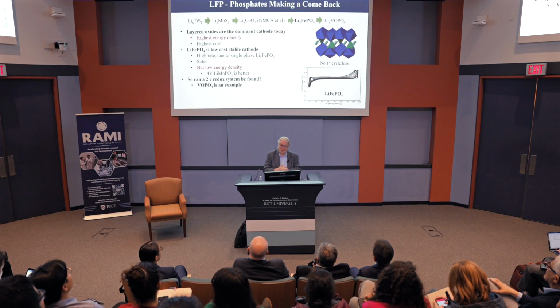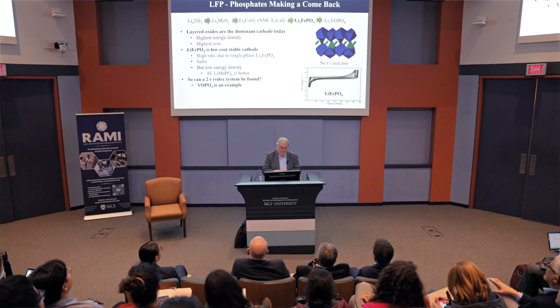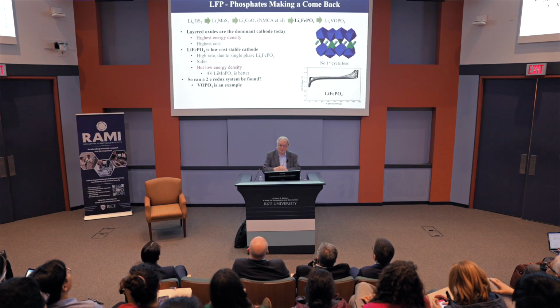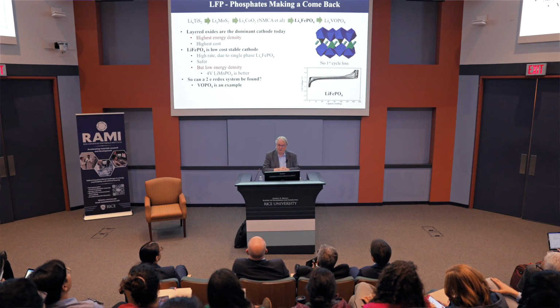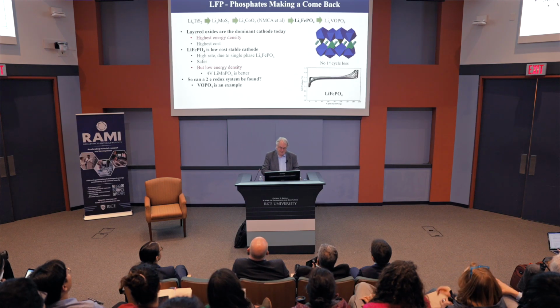Strangely, it has one of the highest rates of all cathode materials. Now, I'll get into that in the next slide. The other plus I've already mentioned, all those elements are available in America. Okay, it's safer. This material does not lose oxygen on heating, so it doesn't have its own source of oxygen inside. We're looking at the 4-volt manganese version, and we're now looking at the vanadium phosphate.